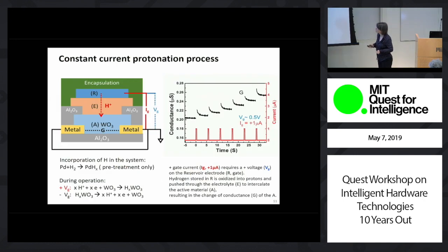Okay? So what we are doing in this first conceptual device that we have demonstrated is that we start the hydrogenation of the palladium layer from gas phase, which is pre-treatment only.